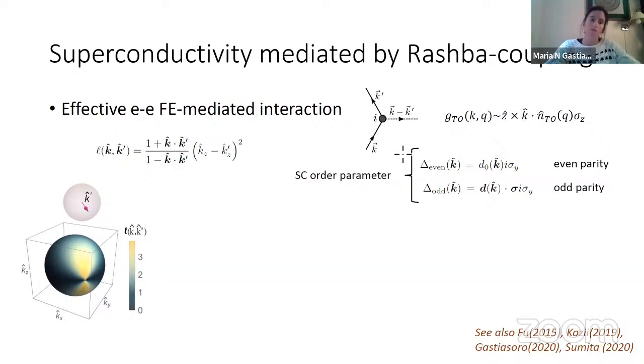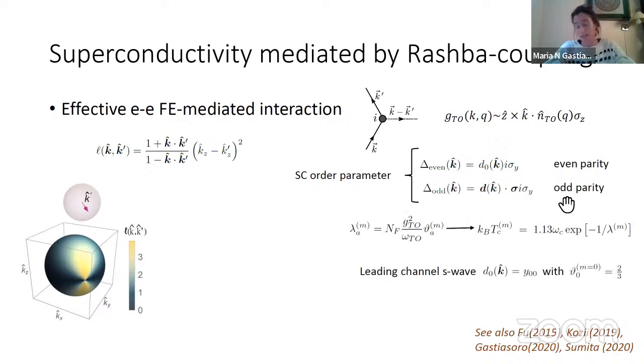And then what we did was solve the Cooper pairing problem by looking at both even and odd parity solutions, which might not be very common to do for phonons, but in this case, because it's a particular phonon, you have this weird vertex. It was already pointed out here that you could have odd parity solutions. And indeed, that's what we also found. So you solve the Cooper pairing problem. That means that you get an eigenvalue for each different channel, and that gives you a hierarchy. And then you look at your top 3, top 4, and see what kind of superconducting states are attractive and allowed by this Rashba-like coupling.